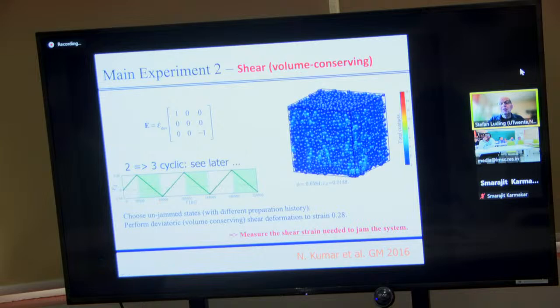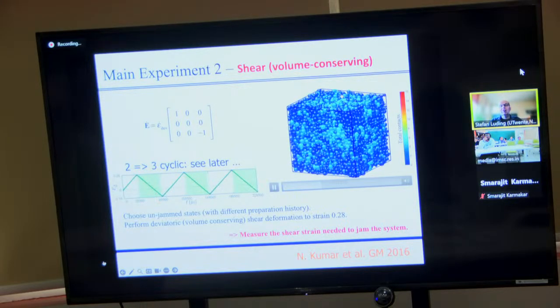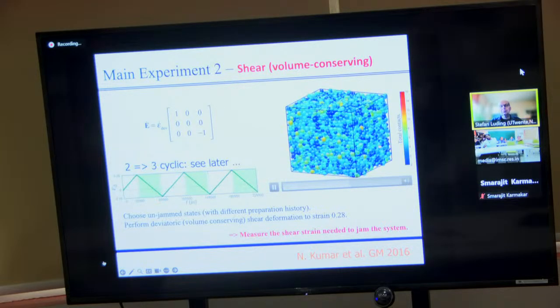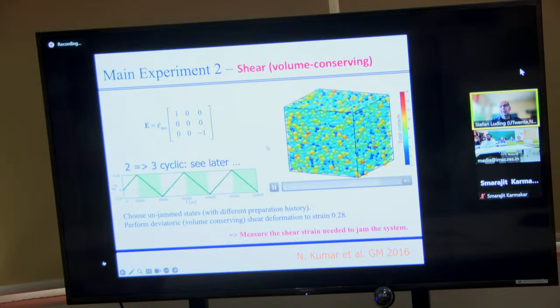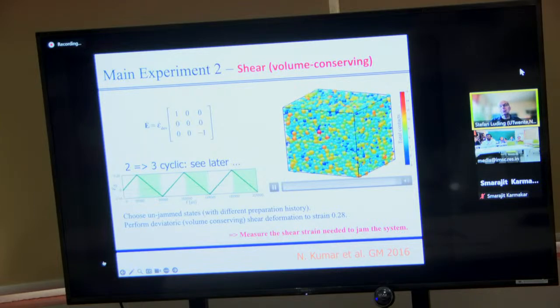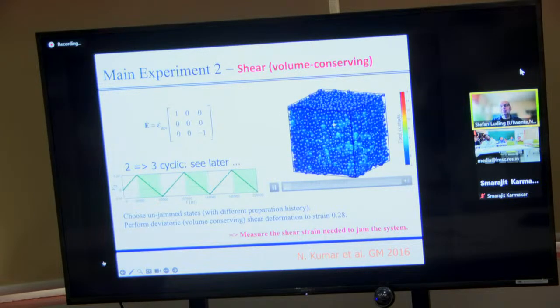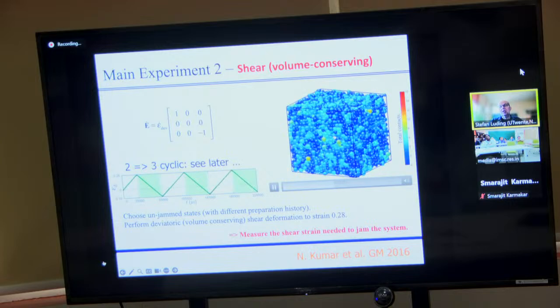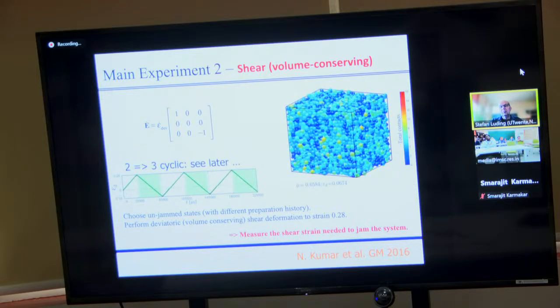I showed you the shear results already, so I don't want to repeat those, but I want to show you an animation of a shear event. Shear here is pure shear, so we have compression vertically and extension in one horizontal direction. The color means how many contacts a particle has. So blue is 0 and yellow and red are high numbers. So it starts again from the beginning. At a certain point we get fragile, so a lot of bluish particles, and then it jams here. Elastic. Elastoplastic, I should say.